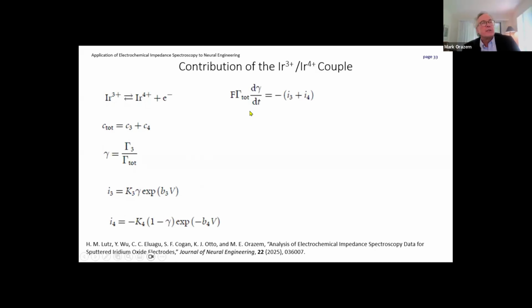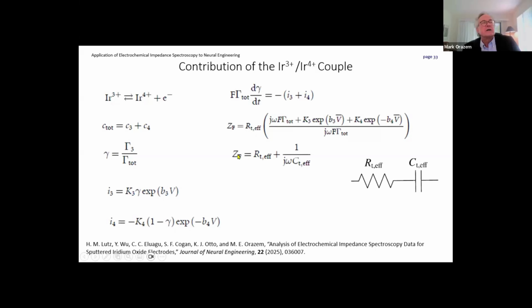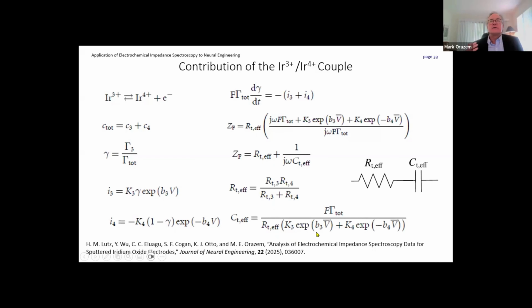And we need one more equation to solve this problem, which is basically a conservation equation for this fractional coverage gamma. And in the end, we have an expression for the Faradaic impedance that can be expressed in terms of a charge transfer resistance and a capacitance. And the capacitance is not the typical capacitance we expect for charging of a double layer. It is associated with the rate constants for the reactions. And this work was in that paper that we published in Journal of Neural Engineering.